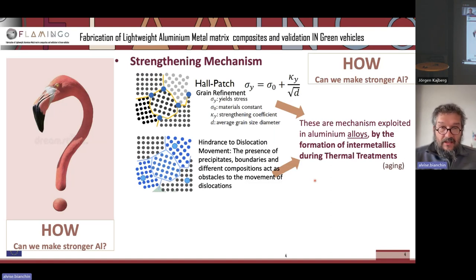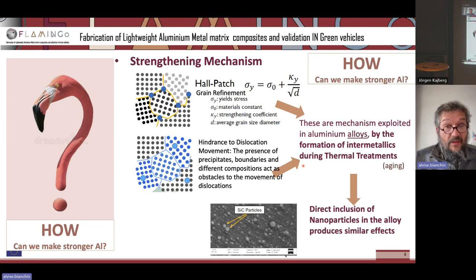So one question that we asked ourselves from the beginning of the project is how can we make a stronger aluminum, considering the strengthening mechanisms that are already considered for aluminum, such as the Hall-Petch and the Orowan mechanisms. We realized that all these are basically derived from the availability or the creation in the melt of nanoparticles. This is well known, and this is also possible to reach thanks to the direct inclusion of nanoparticles in the alloy. And this produces a similar strengthening mechanism and similar effect on the overall alloy.